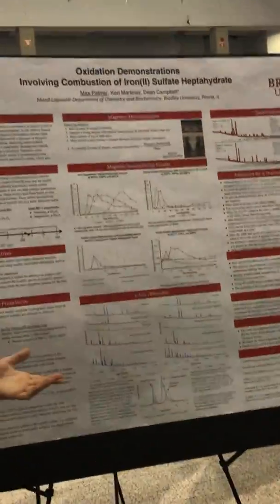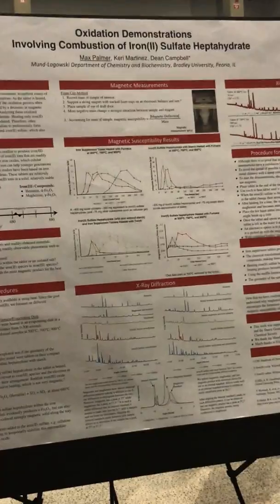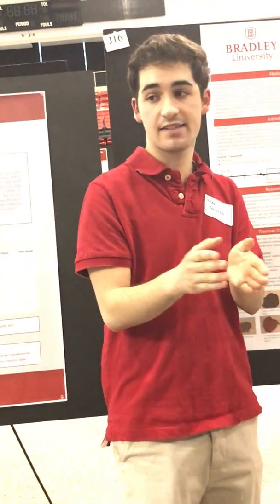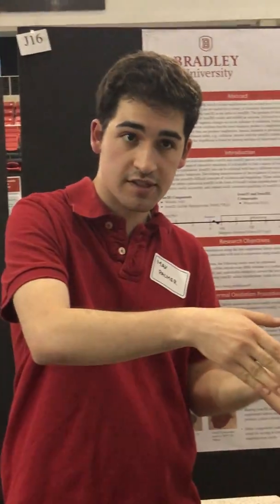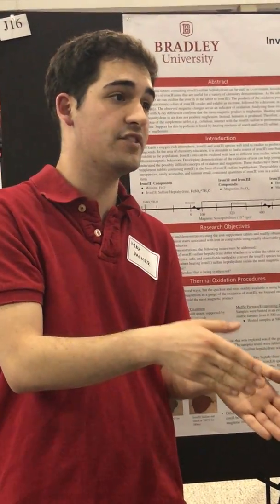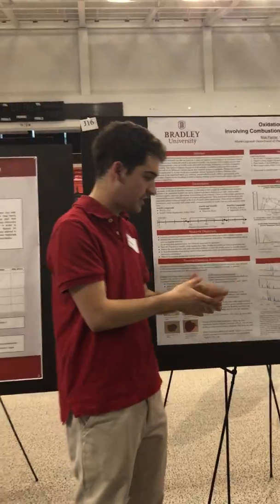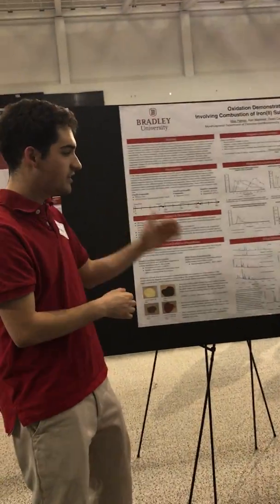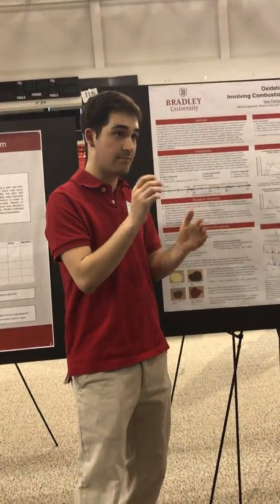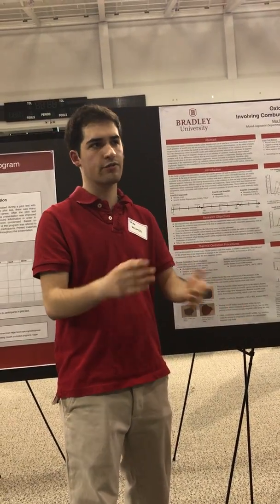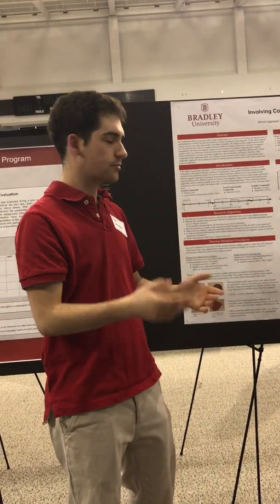So we actually found a paper that says if you look at the angle 57 degrees when you shine X-rays at it, magnetite has a peak at 57 degrees and maghemite has a peak at 57.3 degrees. There's a few other peaks that are a little off like that, but we focused on the 57. So we needed to make sure that that minute shift was natural, and it wasn't human error or from the instrument that we were using.